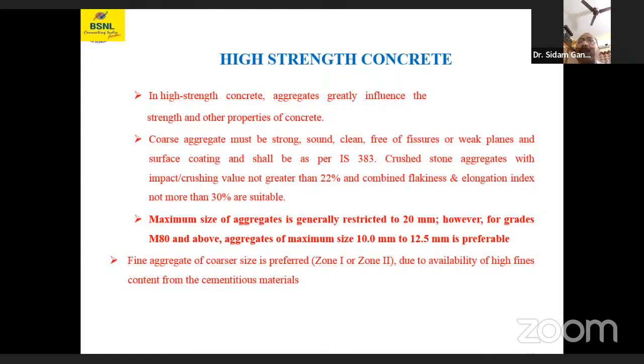In high strength concrete, aggregates greatly influence the strength and other properties of concrete. Coarse aggregate must be strong, sound, clean, free of fissures or weak planes and surface coating, and shall be as per IS 383. Crushed stone aggregates with impact or crushing value not greater than 22% and combined flakiness and elongation index not more than 30% are suitable for high strength concrete.